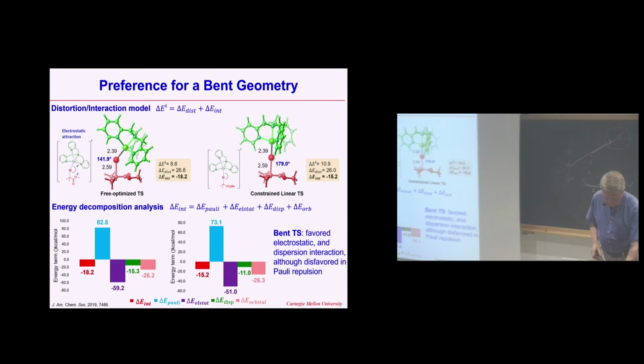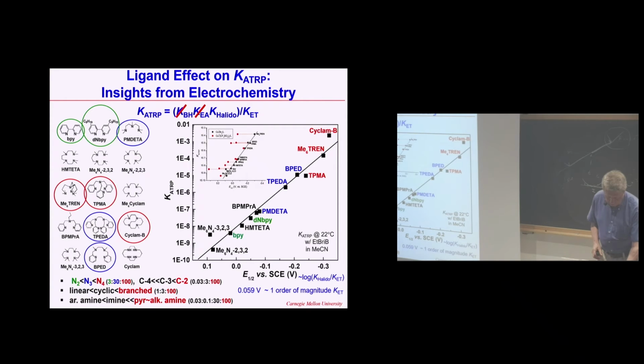Okay. Yeah, maybe I can skip some of these parts and tell you a little bit about how you can go to the designing of a new catalyst. So you have many ligands. They are nitrogen-based, most active in fact. And it looks like for the distance between carbon atoms, between two different nitrogen atoms, the better is 4 than 3 than 2. Also, if you look at this, this is the number of nitrogen atoms. This is the carbon bridge. 2 is better than 3 than 4. Typically, we want to have branched structures, and then pyridine or alkylamines.